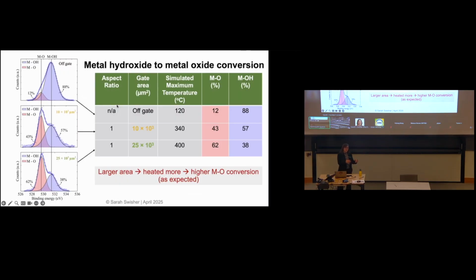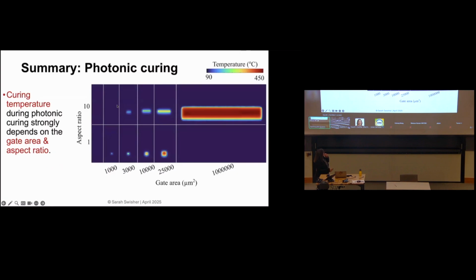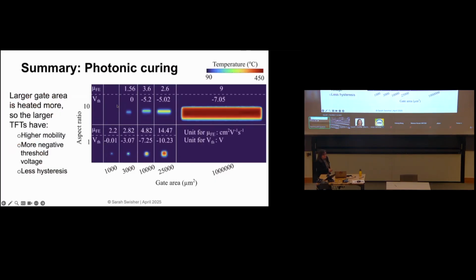So both the transistor performance and this measure of the chemical conversion are confirming this 3D model that says, yes, area matters. Yes, the design of the gate geometry matters. This is the first time that this was shown. Here's just a short subset of the devices. This is aspect ratio 1. These are squares, these are rectangles, and each column has the same area. You can see pretty clearly that by decreasing the area here, the temperature is going down, and by going from a rectangle to a square, your temperature is going up. That corresponds to the mobility getting higher as the temperature goes up, which is exactly what we expect, and the threshold voltage becoming more negative as the temperature goes up, which is also exactly what we expect for these materials.